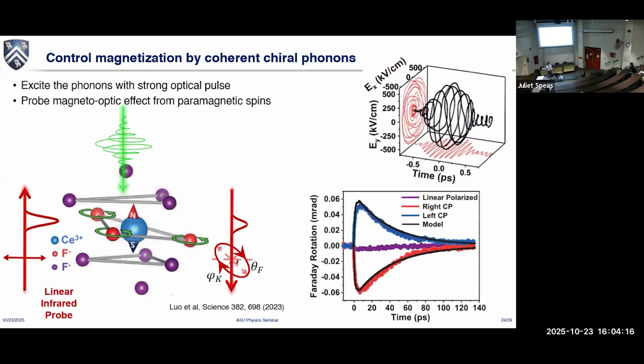And then putting this pulse into the material would cause the atoms to actually rotate. And as expected, when the surrounding atoms of the crystal field start to dance like a hula hoop, then the center ions, which are rare earth paramagnetic, you will see that the spins actually start to polarize as if placed under a magnetic field. Okay, so this is pretty nice. Everything is time resolved. You can see that the spins start to quickly develop when we inject phonons, and then when the phonons are dead, because these optical phonons live at the picosecond level, the spins start to relax again. So this is typical paramagnetism.